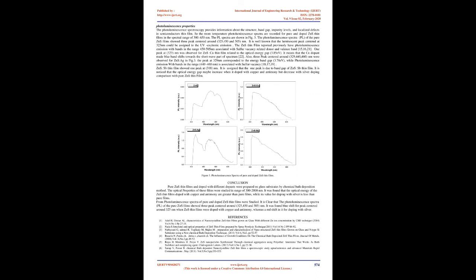It was found that the values of optical energy gap of the ZnS thin films doped with copper and antimony are greater than pure films, while its value for doping with silver is less than pure films. The increase in the bandgap of Cu-doped ZnS film can be related to the structural modification of the ZnS thin film. It can also be supposed that the copper ions can replace, either by substitution or interstitially, the zinc ions in the ZnS lattice, creating structural deformation.